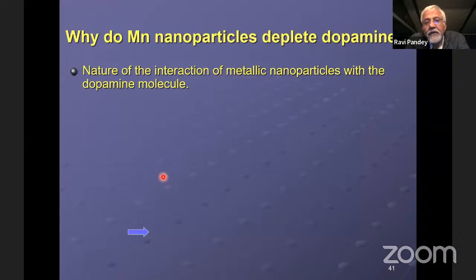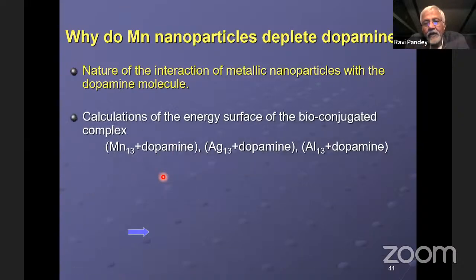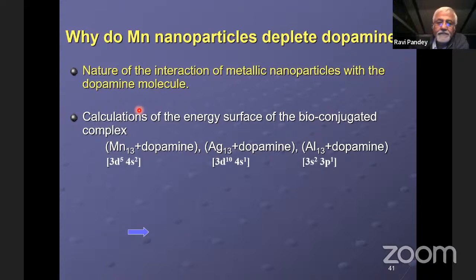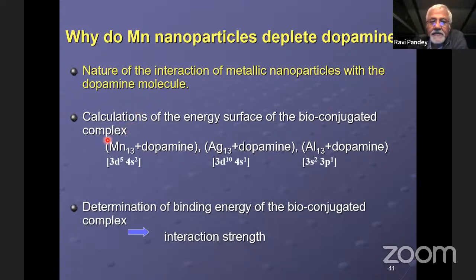So we thought, okay, let's start with the question, and we look at the so-called nature of the interaction of these nanoparticles with the molecule, because we've got to start from somewhere. And so we take these nanoparticles and see if we can calculate the energy surface when they're forming the complex. So we have the manganese 13 nanoparticles, and we picked a 13 atom cluster because it's symmetric, it has an icosahedral symmetry. So that's the advantage in our calculations.